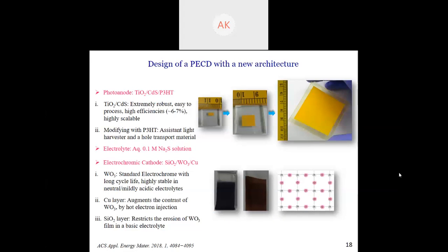Okay, Ankita, should we go on to the next question? Ankita, I have one question connected to the previous one. In the SILAR method, how are you confirming that the selenide or sulfide species is binding to the cadmium on the TiO2 layer? It cannot bind to the TiO2 layer directly because we have first coated it with Cd2+, so there is Cd2+ everywhere over the TiO2. How are you confirming the uniformity of the Cd2+ over the whole active area?